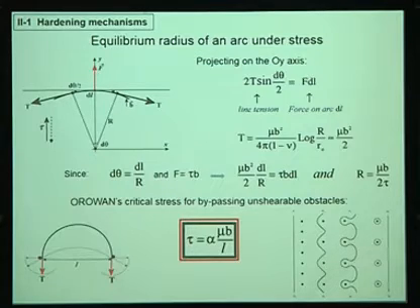Okay, is everybody clear? Is this clear for you? So you compensate F by those two projections of T along the y-axis. And T, as I said, is the line tension. We did it in the lecture yesterday. It is the energy, mu b squared over 4 pi (1 minus nu), with a logarithmic term because it was integrated. Okay, so if you put that together, and if you replace r d theta with dl, because it's a curved line, r d theta is equal to the length of your arc.